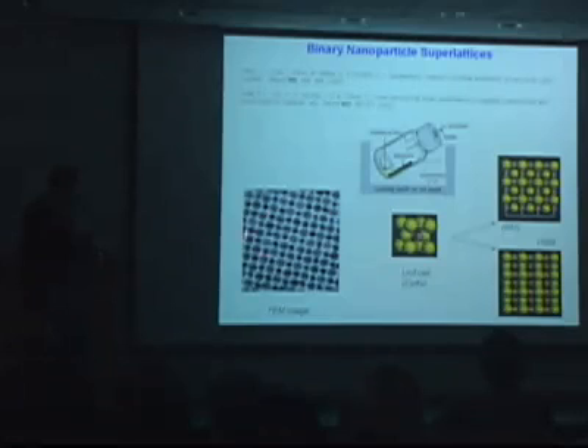In many cases, for example, this particular structure is isostructural with the copper-gold intermetallic compound. So this is a type of unit cell that you can find by doing transmission electron microscopy along different zone axes of the crystal structure, using tilting experiments. And we name these structures following their unit cell type.